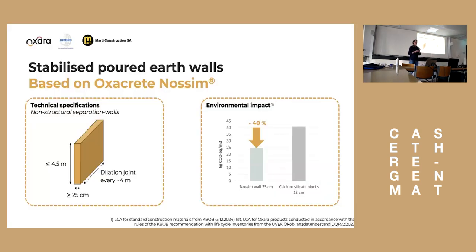And here, quickly, the technical specifications summarized. We recommend for this poured earth wall a thickness larger than 25 centimeters, and a maximum height of 4.5 meters, because if you go higher, it really gets tricky to demold the walls. If you would have a prefabricated process, maybe it's a different story, but if you want to demold, you need to have enough strength to be able to take away the formwork. And if you don't want to overstabilize, there is a limit in height. And you need to plan dilatation joints, we say every 4 meters, to avoid shrinkage cracks.